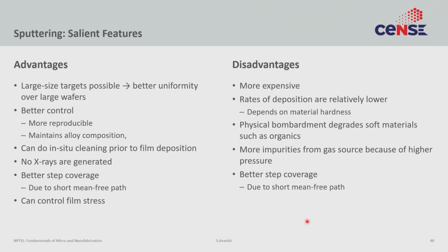With that, let me start to conclude and firstly discuss some advantages and disadvantages of sputtering. So the great advantage of sputtering is that large size targets are possible. If you remember when we were discussing evaporation, we had point sources, we had crucibles, we had resistance, but we didn't have things that were very large in size. And that meant that we always had this optimization issue of substrate to target distance versus uniformity. In sputtering, because of the way the sputter gun is made, you can make arbitrarily large targets, and that means you can make arbitrarily large areas for uniform deposition.